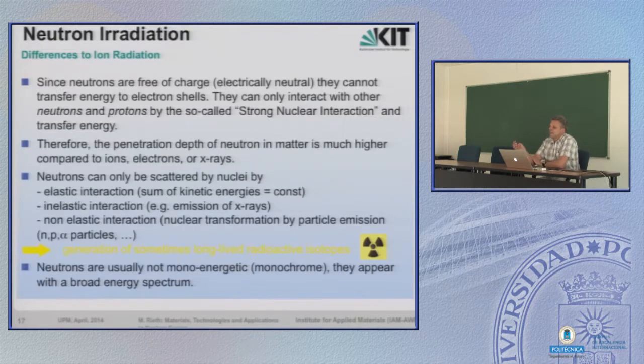So they can only interact with other neutrons and protons, which go back to the so-called strong nuclear interaction, and by this interaction they transfer energy. Therefore, the penetration depth of neutrons in matter is much higher, as I have already explained for the comparison in steel, where we have 1 meter or so in the given example. But also, neutrons can only be scattered by nuclei, which means there is an elastic interaction, where the sum of kinetic energies is constant, or inelastic interactions, which again produce emissions of light, in this case most often X-rays, but there are also non-elastic interactions.